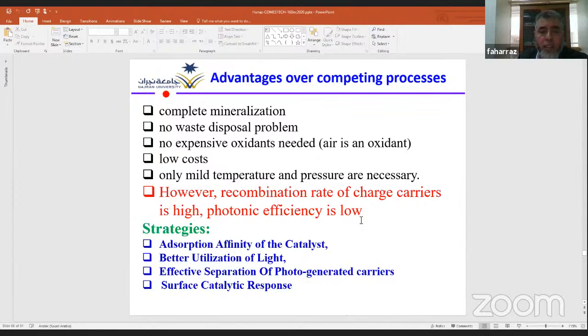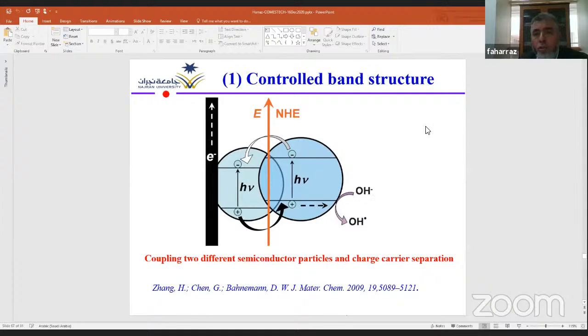A strategy to solve these drawbacks is to find suitable nanomaterials that increase the adsorption affinity of the catalyst, enhance the utilization of light, make an effective separation of the photo-generated carriers to decrease the recombination rate, and also enhance the surface catalytic response. For these strategies, there are two main routes. The first route is coupling two different semiconductor particles in a way that helps you control the band structure. This picture shows coupling between two semiconductor particles. In this way, charge carrier separation is enhanced.